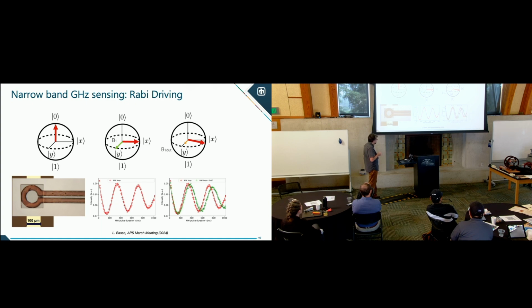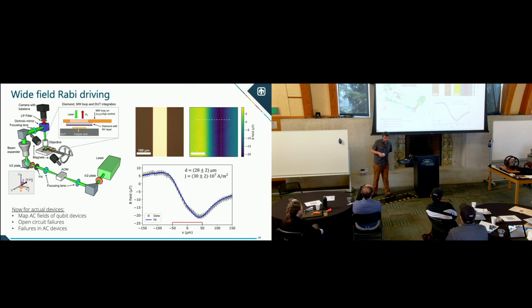In this case, it was just a wire as proof of principle. And so you can actually get 4 orders of magnitude weaker than your microwave drive going through the sample to see these slight changes, and map that out just like we did with the DC field. So we can still project that onto a camera.